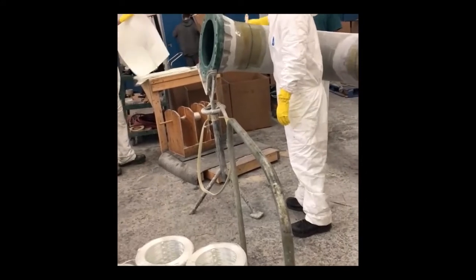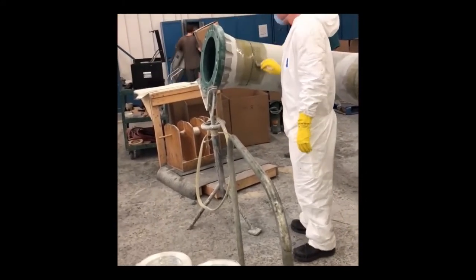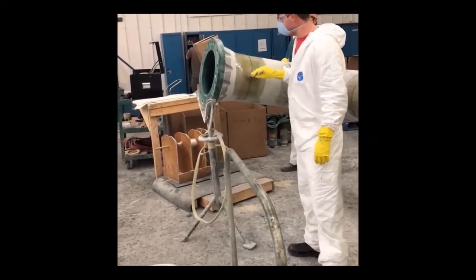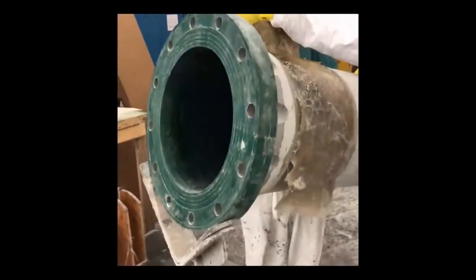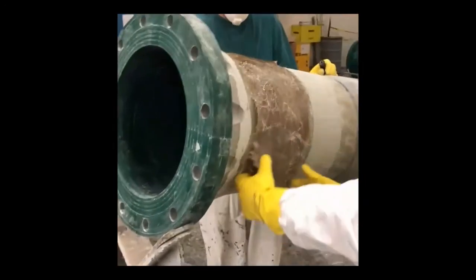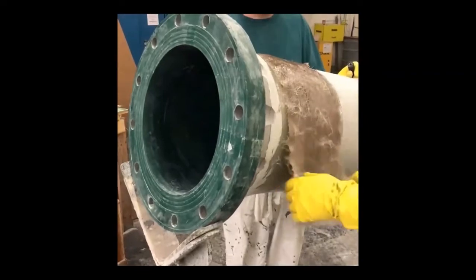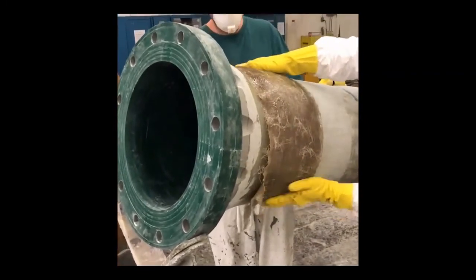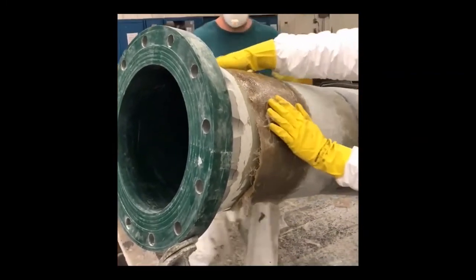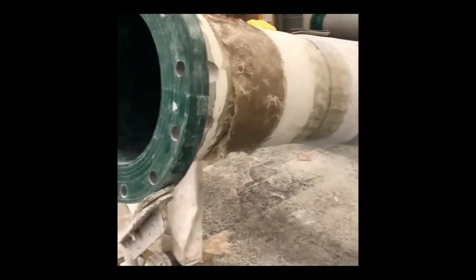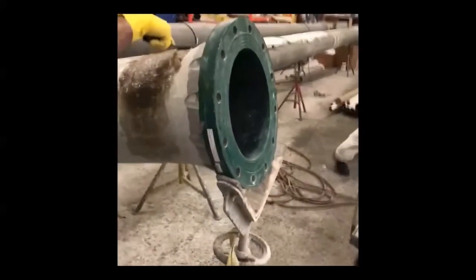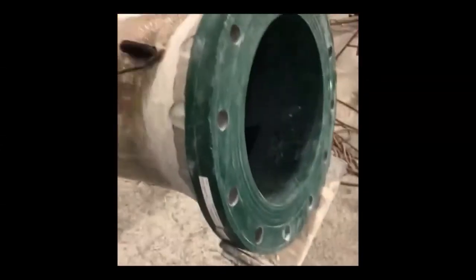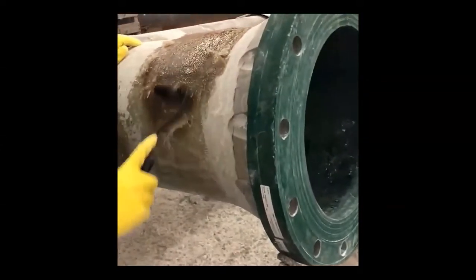Now he's going to go over and pick up the laminate that he's saturated with the resin and lay it down over the seam, center it over the seam. You can see it's all kind of rough and uneven and probably full of air. So what the other technician is going to do is roll out that laminate. He's going to roll out all the air in the laminate and compact the layers. And as you can see, it's a bit of a craft.